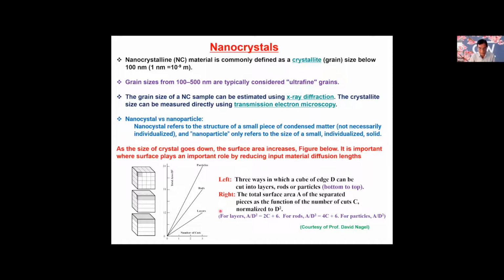And here is something very interesting. As the size of the crystal goes down, the surface area increases, as I mentioned before, and it is given in the figure here. It is important to note that surface plays an important role by reducing the diffusion lengths in materials. So the diffusion length gets reduced, and so the material can be loaded faster.